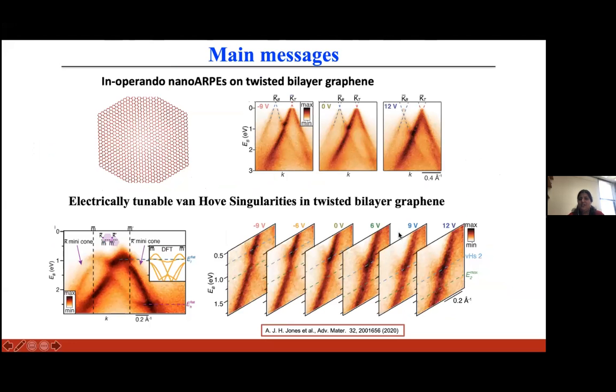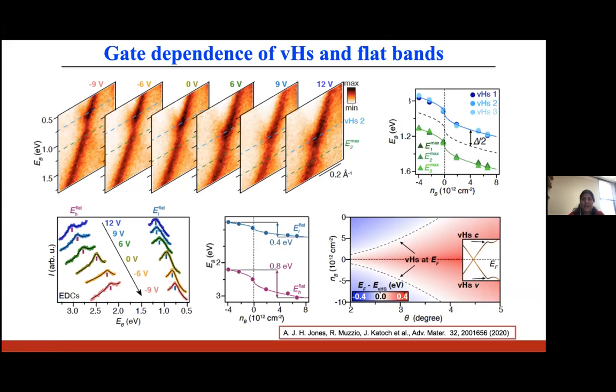And similarly, we observe the same square root n dependence for these flat bands. And interestingly, we find that this flat band at a higher binding energy can be tuned by doping more, almost double as compared to this lower flat band at a lower binding energy. And this is due to the combination of the fact that we have different charge induced in the two graphene layers, and, as I said before, the shifting for the higher binding energy flat band is taking place in a highly nonlinear, collinear part of the bottom Dirac cone.